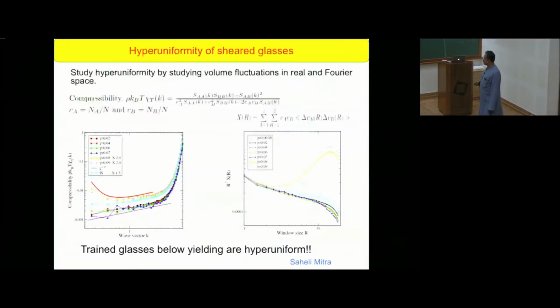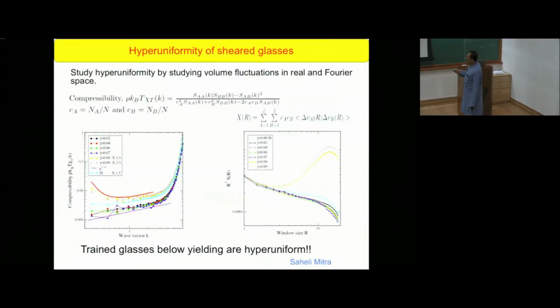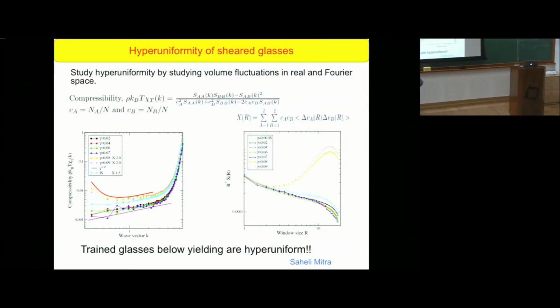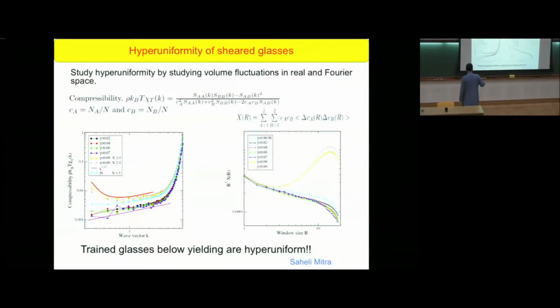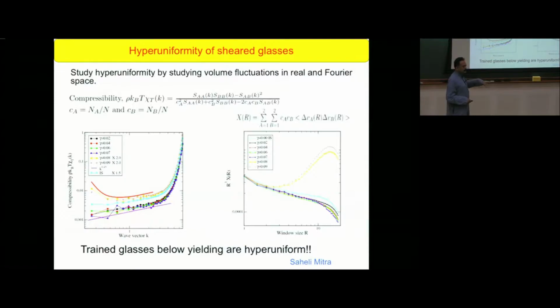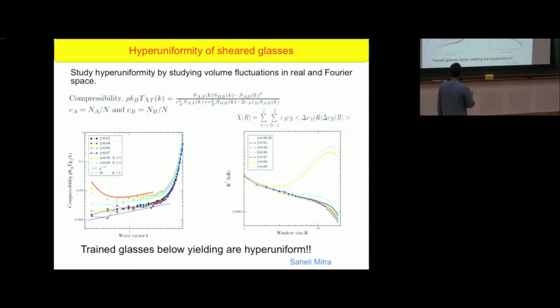This is from other people's work. This is from our work, where this is as good as it gets. Below the yielding, all these curves are below yielding, and you see that for the largest sizes that we have, we do have a power law which is not changing as I go to lower wave vectors. But when I go past the yielding transition, there is a change that makes these curves go up to finite values. So there is a hyperuniform to normal transition when you go through the yielding transition.